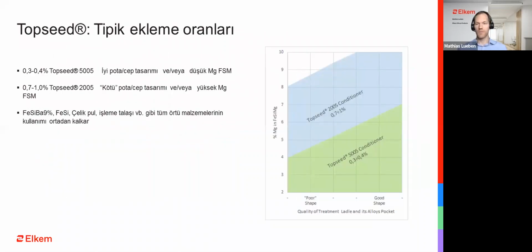Typical addition rates of Topseed are 0.3 to 0.4% of Topseed 5005 for well-designed ladles and pockets, and a low magnesium containing FSM. About 0.7 to 1% Topseed 2005 is recommended for, let's say, poorly designed ladle and pocket and a high magnesium containing FSM. To explain it a little bit, a poor ladle is a ladle with a low ratio between height and diameter, no pocket, or also a low ratio, or a pocket so tight that it's really hard to clean.